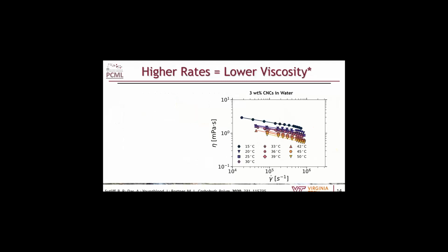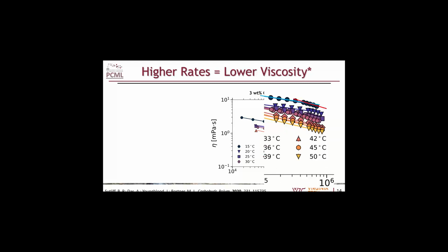Before we get to that, there's another error we noticed: if you look right about 400,000 reciprocal seconds, you can see a slight increase in our power law once we get above that. The slope of our line changes to a much steeper slope. So we wanted to look at viscous heating above this point.